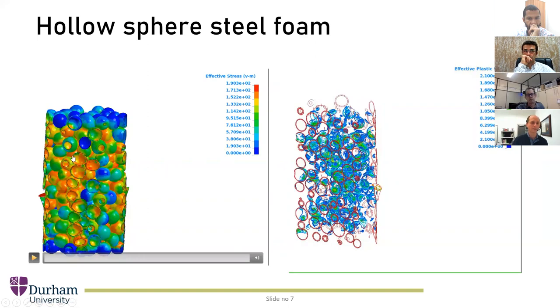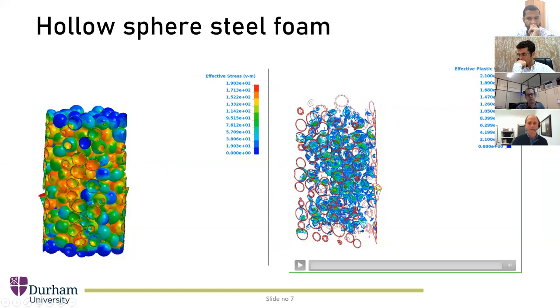So what we found there is that the heat will mostly affect the yield stress, and the yield stress will affect the plastic buckling capacity, because these spheres buckle plastically. So the buckling is not controlled by the elastic Young modulus, but by the yield stress, sort of it's in the material controlled regime. It will kind of linearly translate in the loss of properties. So the yield stress will control.